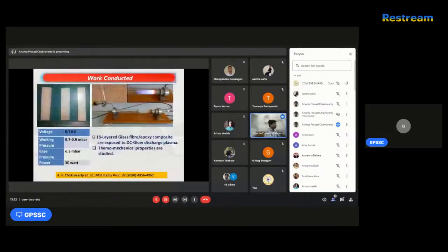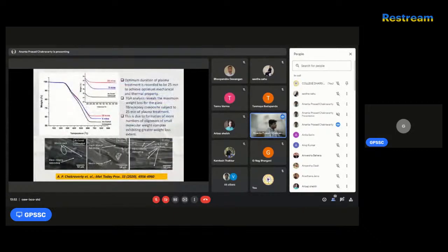Now, keeping this in mind, I have another work where I exposed this kind of material to plasma with respect to these parameters: voltage, working pressure, and a power level of 30 watt, as I have mentioned. With respect to that, when I went for thermogravimetric analysis, I saw different weight loss behaviors, and after 25 minutes I can see the minimum weight loss.